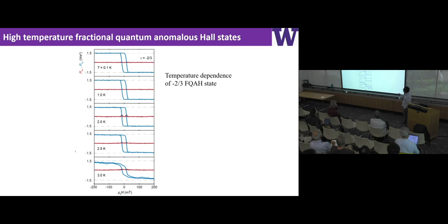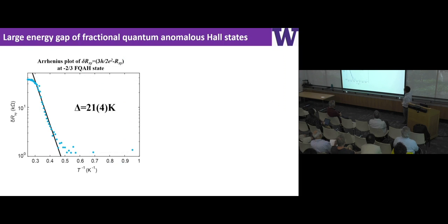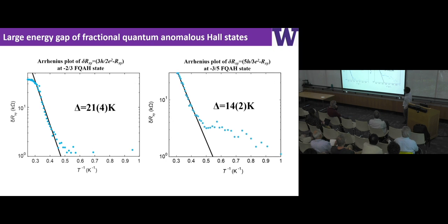I still want to emphasize that this feature is at high temperature. So what I show you here is the data from the 2/3 state as a function of temperature. From the top to the bottom, I increase temperature from 0.1 Kelvin to 3 Kelvin. What I highlight here is that even at 2 Kelvin, the state is still nearly quantized. So this basically tells you the energy gap is pretty large. And we can perform these thermal activation measurements again, and they give us a gap for the 2/3 state of around 20 Kelvin, and for the 3/5 state about 14 Kelvin.